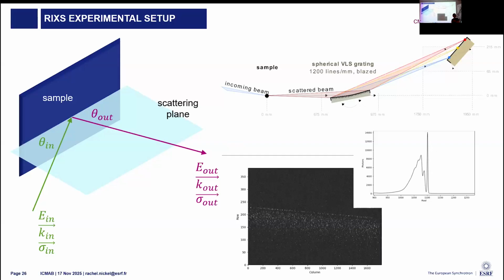If we take those at various energies, we can use it to construct an energy-dependent RIXS map. If we take it at various Q points by rotating either the sample or the spectrometer, you can resolve a RIXS map in momentum space. So this is a very versatile technique. It helps if you know what you're looking for before you start measuring.